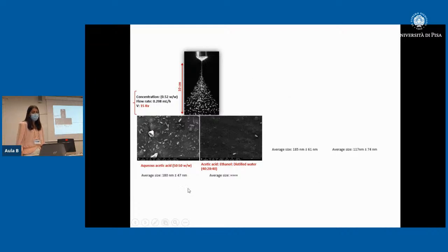So with changing some parameters of electrospray technique, we reach to the different results. As you can see, for example, by using different solvents, we reach to the nanoparticle with different morphology and size. Actually, by using acetic acid, ethanol, and distilled water, we couldn't reach to the very separated particles. They were aggregated. But by using aqueous acetic acid, we got good results. You can see the nanofibrils are in a uniform shape and nanoscale size.